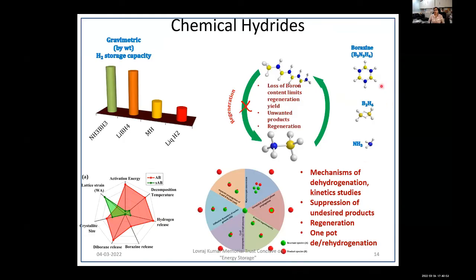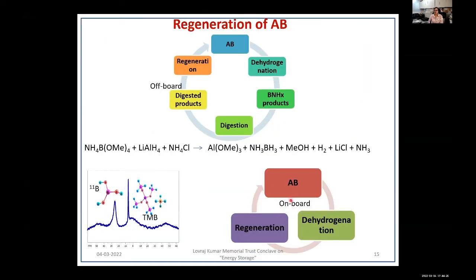Now what we are doing is working on the regeneration. These materials regenerate in different steps, so you cannot do on-board regeneration; it has to be a 2 or 3 step regeneration. Now we are able to make it a single step regeneration, and the yield that we could get is 85% in the regeneration step, in a single step, 1-pot synthesis and dehydrogenation. So instead of having multiple steps, we just dehydrogenate it and put the hydrogen back, so that this could be suitable for on-board application, and still we can get about 13 weight% capacity with such materials.